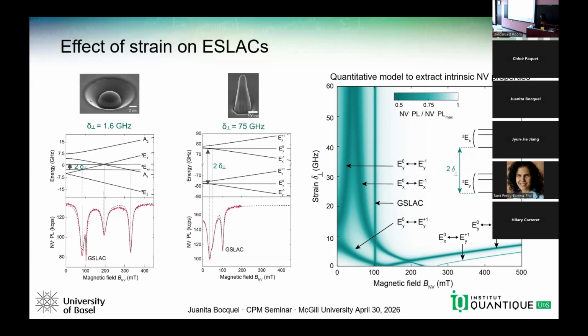experimentally. And that's in a way too bad, because for the experiment, you want to be out of those regions where you have degraded spin contrast. And you can see that one solution is to apply magnetic fields, but again, this is not always available for all experiments in all platforms. And the other is to have extremely low strain, but again, as soon as you go into a nanofabricated structure, you typically always find yourself in that regime where at low magnetic field you have degraded spin contrast through mixing.